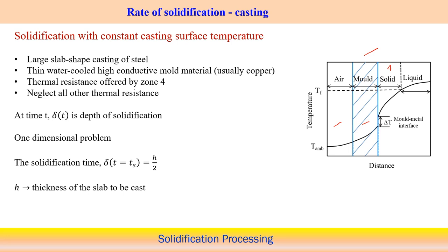A thin, water cooled, high conductive mold material is usually used. That means a very thin mold surface as well as water cooling, so the heat dissipation rate through the mold surface can easily be increased, and the thermal conductivity of this mold material is very high. Usually we use copper as the mold metal, and in that case the thermal diffusivity is very high for copper.